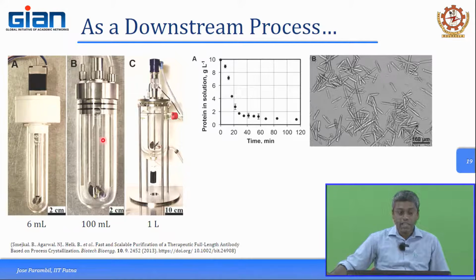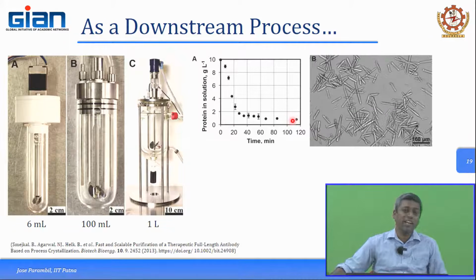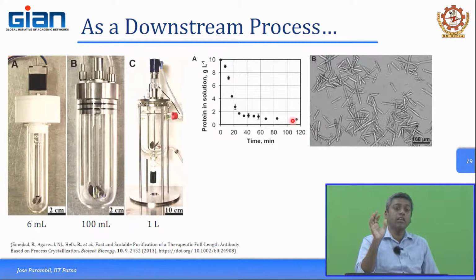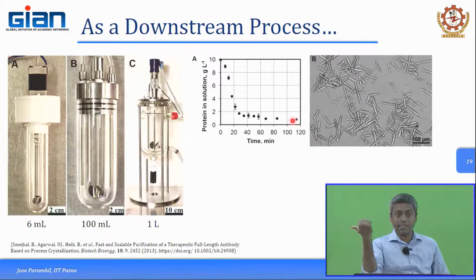liter vessels. The geometry looks pretty similar, similar sort of mixing patterns and so on can be implemented, temperature profiles, etc., can be implemented, and you can see that during the crystallization process, the antibody concentration basically decreases from 10 gram per liter to practically around 1 gram per liter, which means that about 90% of the antibody which is there in the feed concentration, you are able to recover it as solids in the crystalline material.